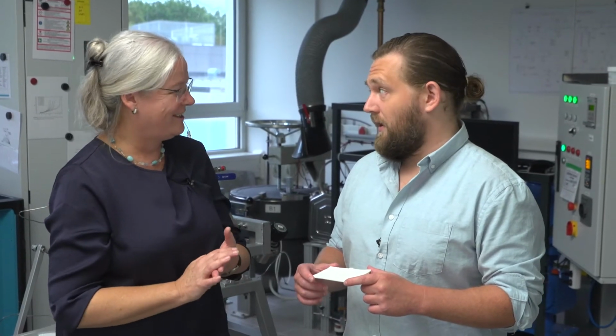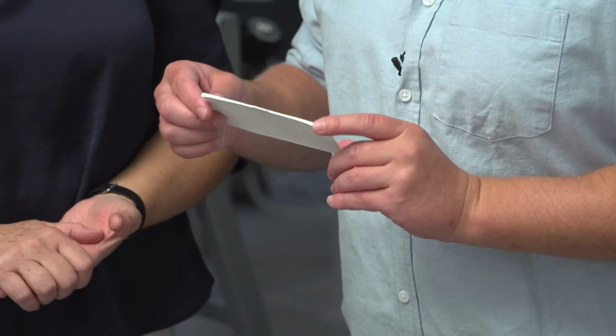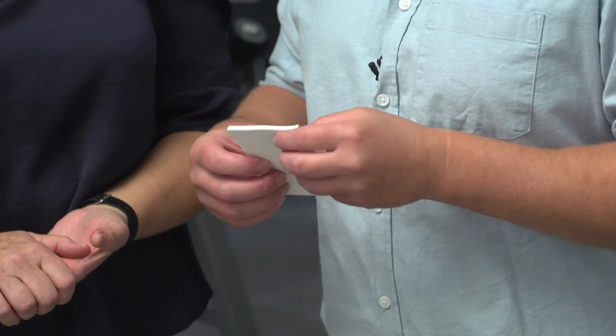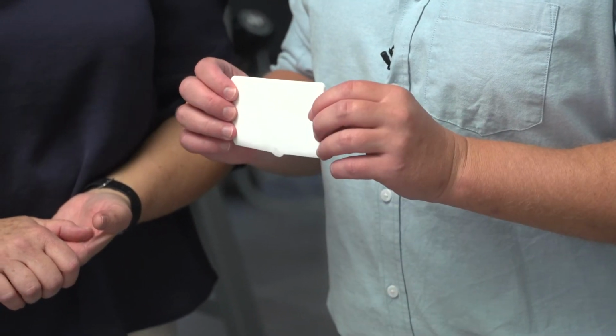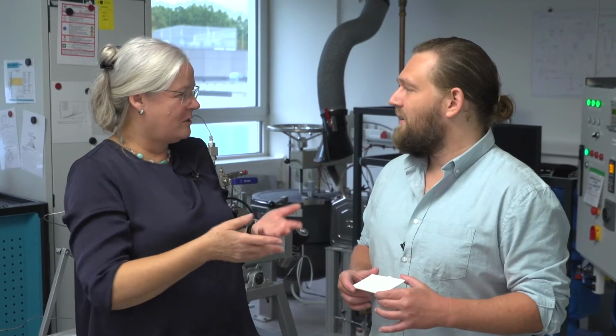You know, cellulose is not easy to dissolve, right? Well, cellulose is the structural fibrous material that gives the structural properties to things like trees and grass and corn, right? Therefore, it has to be hard to dissolve. It should not be dissolved in water. Cellulose natively is very hydrophobic or water resistant. Is this material then also hard to dissolve and water resistant? It is not water resistant. Cellulose is, but the structure isn't. The aerogel's not. That's because of its pores and all the hydrogen bonding, and if you have the water coming in, it shrinks.